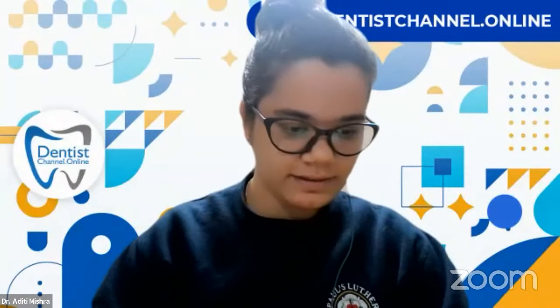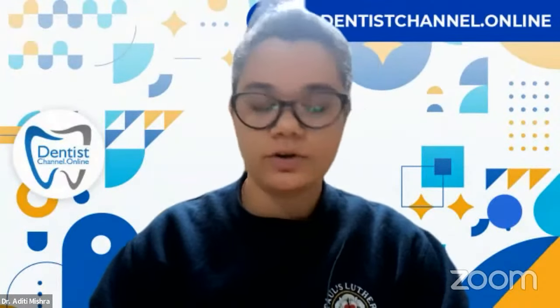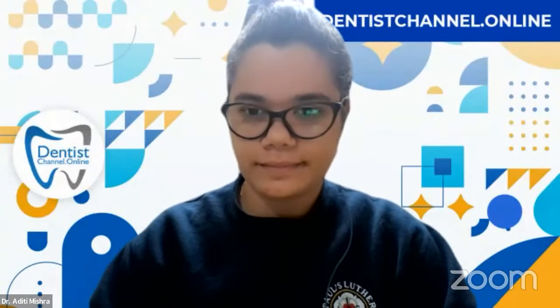Right. Thank you. So next question is, is it okay to grind on a zirconia coping without water spray? No, generally, we always recommend to grind zirconia with water cooling. It's a really important thing because the zirconia material reacts really badly to overheating. And this is correct for the complete workflow, not just for grinding, but also for ceramic layering. So you have to always pay attention to the heating phase and the cooling phase, because zirconia itself handles heat really badly.